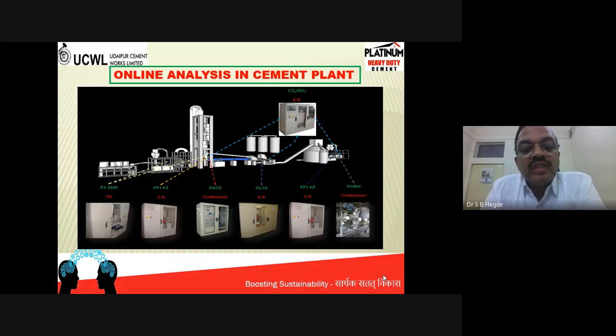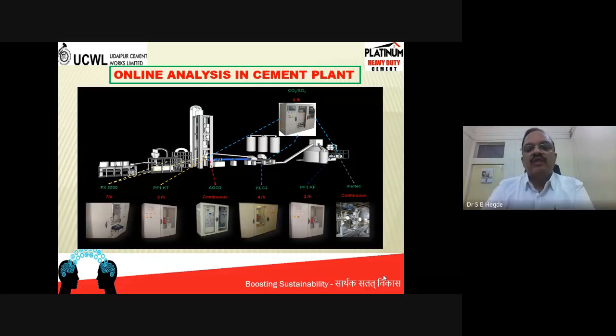And the second box, you can see that this is online loss on ignition, because you must be aware that 100% calcium carbonate has 56% CaO. So if it is 100% calcium carbonate, the CaO content will be 56% and the loss on ignition will be the rest, 44%. So depending upon the requirement of the kiln feed, we are monitoring the online loss on ignition in the cement plant system. It will show the analysis second by second, and people will be there to observe whether it is in line with our requirement or not.